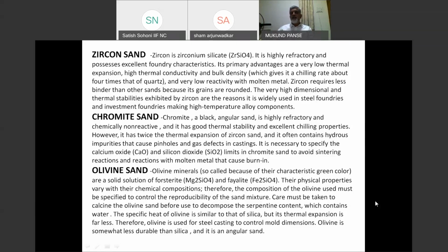Chromite sand is a black angular sand. It is highly refractory, chemically non-reactive, with good thermal stability. Its thermal expansion, though more than zircon, is substantially less. Its chilling properties are very excellent. But the problem is this is a mined sand. This is crushed sand, so you get angular grains, and to get the exact distribution required is difficult. This chromite sand is again used at heavier metal junctions so that the metal doesn't fuse. You have to control the SiO2 percentage in this, because when the free SiO2 is more, it can react with chromite and iron when the metal is poured and form a solid mass, a hard fused mass.